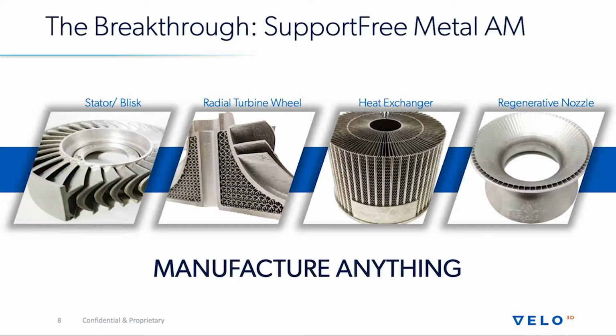It's radial walls. So one of the things that you may have experienced with some of the conventional recoaters is that if you have thin walls that end up being parallel to your recoater blade, when you go to recoat, bad things can happen. And with a non-contact recoater, this isn't an issue anymore. So you can print these high aspect ratio structures in any orientation and not worry about whether or not your parts are square to the recoater.